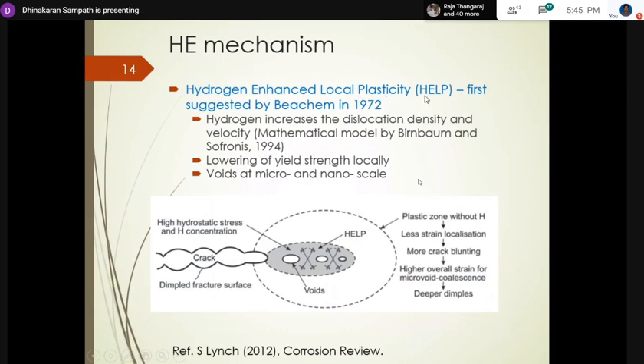Hydrogen enhanced local plasticity, which is a very recent one, but a very comprehensive mechanism, tries to explain several of the observed phenomena in this failure. What it says is, in the presence of hydrogen, dislocation density increases and velocity also increases. So what is a dislocation? It's a line defect, which is actually the basic unit of plasticity. That means it will create permanent strain in the lattice.